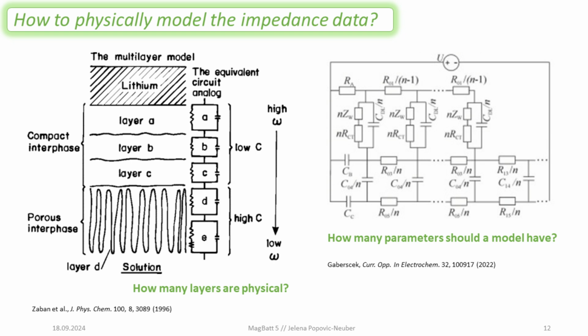And then we have another way of seeing things that is highly complex that comes from the Slovenian group at the National Institute of Chemistry in Ljubljana. That is a model that takes into account that we have a lot of processes taking place, but also that we might have electronic conductivity in our SEI. So that makes our models these kind of transmission line models. These models have quite a lot of parameters, right? I have something like 8 to 12 parameters that I have to somehow fix. So the chemical engineer in me says, yeah, that's fine, but the physical chemist in me says, no, it's not. I don't know what to do with 12 parameters, and I cannot measure them directly, so I do not know if the numbers that I get from this model are actually meaningful.